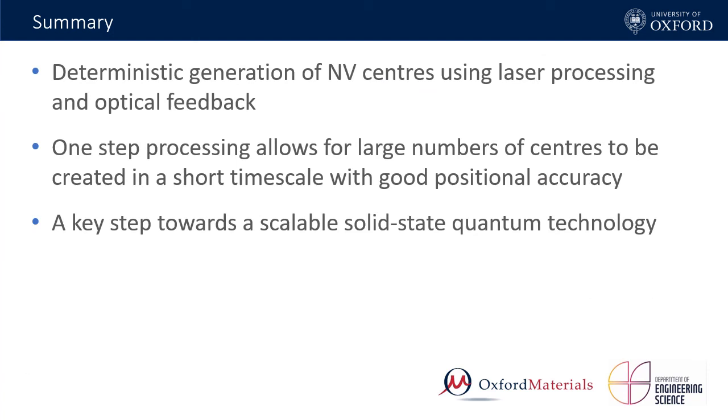In summary, we have been able to deterministically engineer NV centres into diamond using laser processing and an optical feedback mechanism. This one-step processing allows us to generate large numbers of centres over a large area in a short time scale with good positional accuracy. This is a key step towards the development of a scalable quantum technology within the solid state.